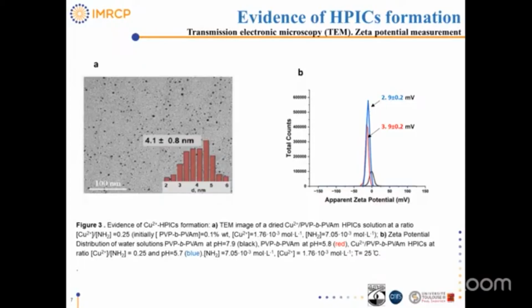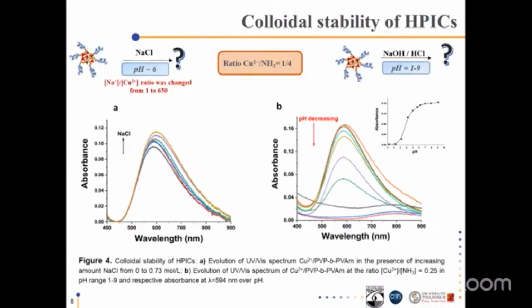It was interesting to evaluate the colloidal stability of HPICs. For this purpose, copper HPICs samples were prepared in the presence of different amounts of 1 molar sodium chloride. As can be seen from the UV spectra, figure 4a, sodium chloride doesn't lead to the destruction of the complex, and HPICs remain stable even at very large excess of sodium chloride.